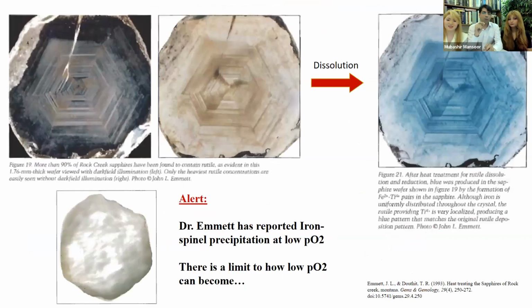Now, we can go further, right? There was a paper published by Professor Emmett where he had actually put forth these beautiful photographs of rutile inclusions before heat treatment and after dissolution, where they have turned blue in color. Something that Dr. Emmett realized was that if you reduce the oxygen more than a particular concentration, so we just mentioned reducing the oxygen is good, but how much? He realized that if you keep on reducing the oxygen more and more and more, you suddenly get a bad effect.